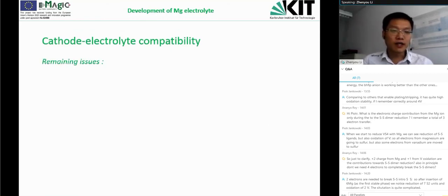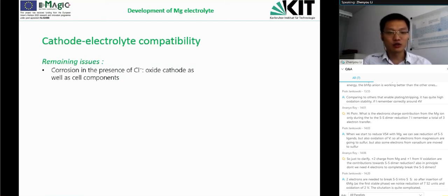In fact, with this non-nucleophilic electrolyte, we have already investigated the magnesium storage capability in a broad range of cathode materials, but there is still the remaining issue, the chlorine. We know the chlorine has multiple functions in the system, but the corrosion is still an issue. This is especially the case for oxides, for example the transition metal oxides, which are still the choice of the market, I would say, in the case of lithium-ion batteries. And it is also a promising high voltage cathode material for magnesium batteries.